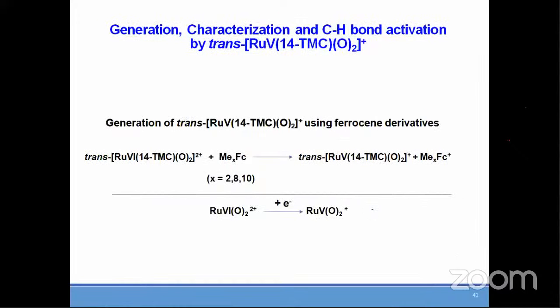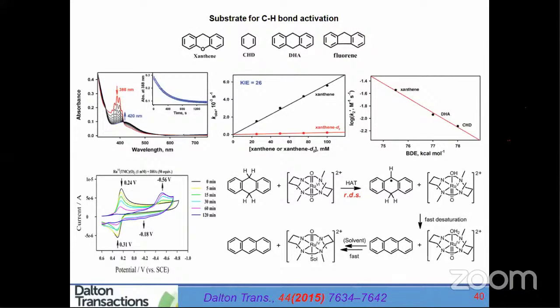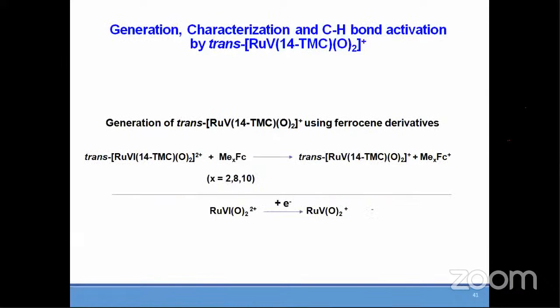Some more work: now we have that ruthenium(VI) dioxo. So we thought whether ruthenium(V) oxo can be prepared. But for ruthenium(V) oxo, our efforts were not successful. In fact, we were able to prepare a ruthenium(V) dioxo intermediate. What we did was very simple. We had the ruthenium(VI) dioxo intermediate, so we thought we will try to use electron donors, ferrocene derivatives. When we used ferrocene derivatives, we were able to get ruthenium(VI) to ruthenium(V) dioxo species.